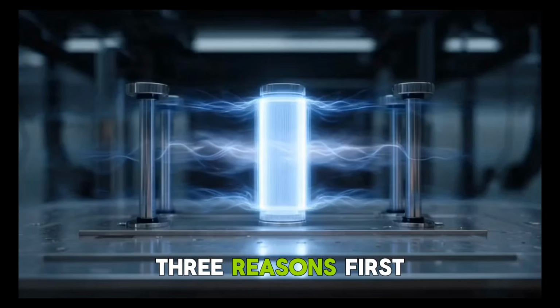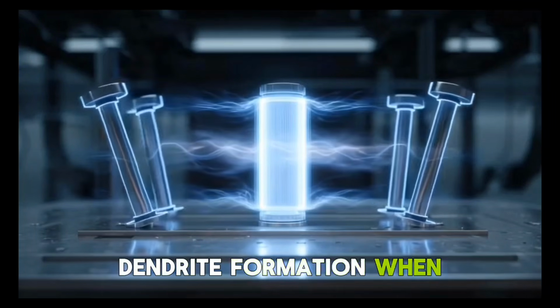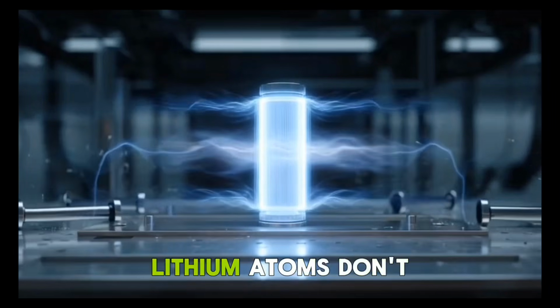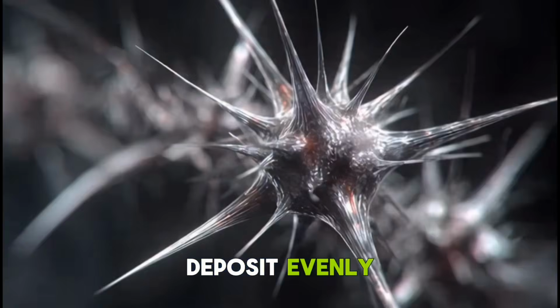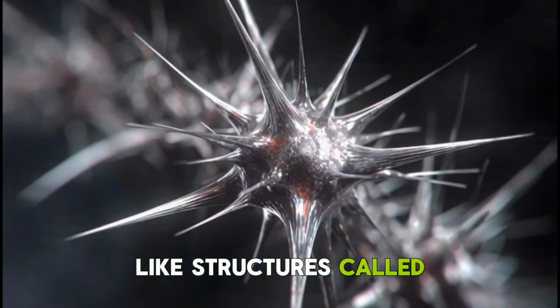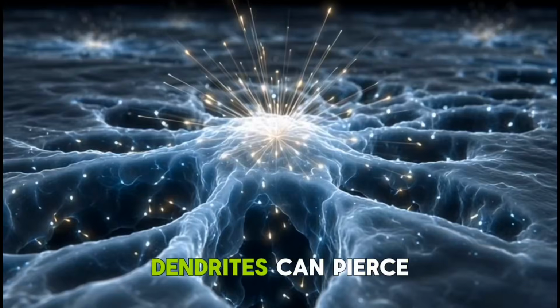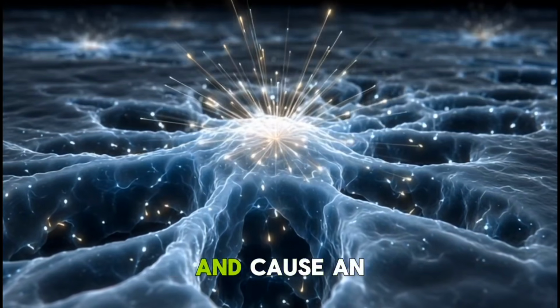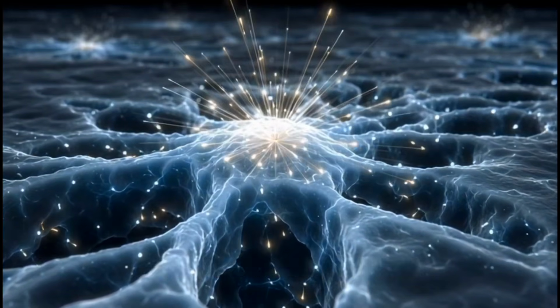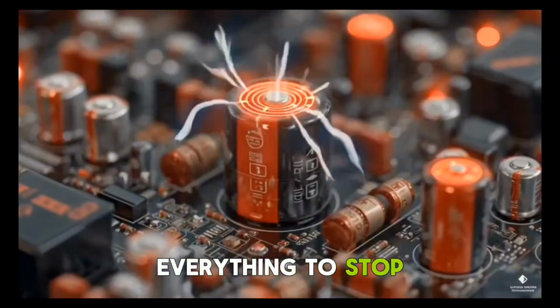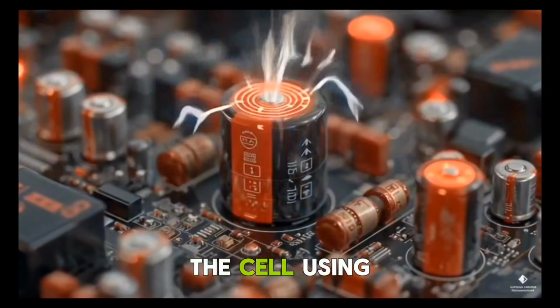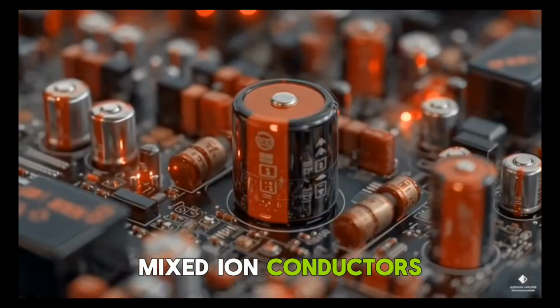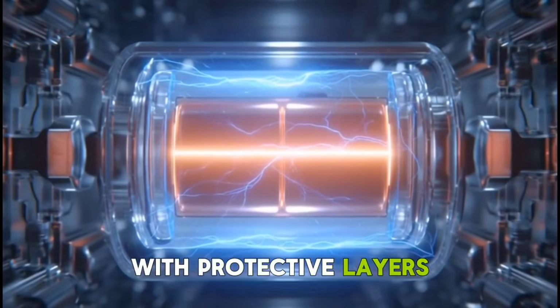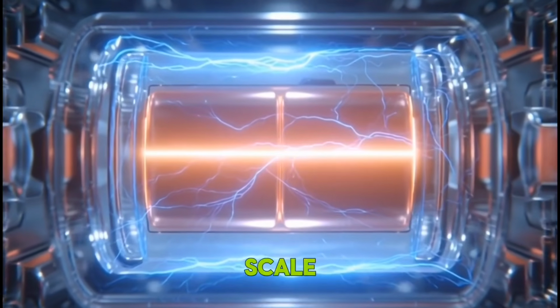3 reasons. First, dendrite formation. When you charge a lithium metal anode, lithium atoms don't deposit evenly. They form needle-like structures called dendrites. Over time, these dendrites can pierce the solid electrolyte and cause an internal short circuit. Researchers have tried everything to stop this, applying pressure to the cell, using mixed ion conductors, coating the anode with protective layers. None of it works reliably at scale.